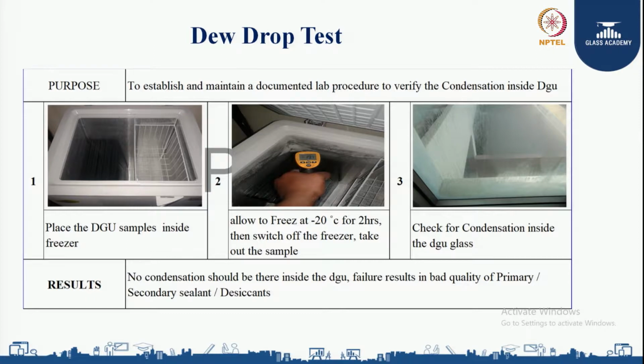So for this test to pass, there should be no condensation inside the DGU. Failure indicates bad quality of the primary sealant, secondary sealant, or desiccant. As shown in the figure, the DGU glass is placed inside the freezer, frozen at minus 20 degrees centigrade for about 2 hours, then taken out to inspect for any condensation inside the DGU.